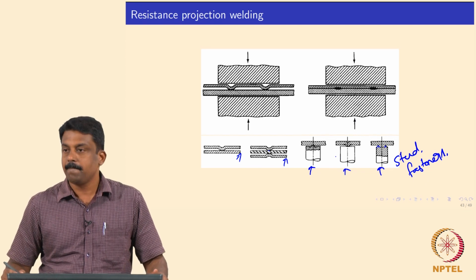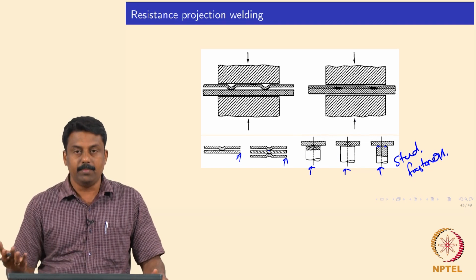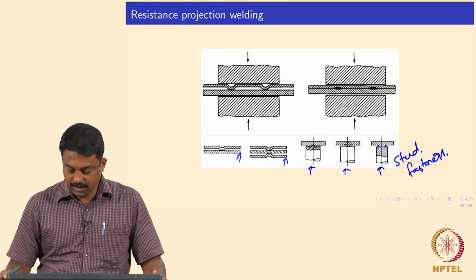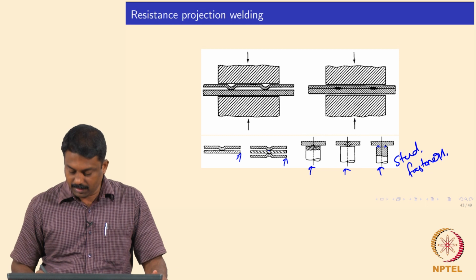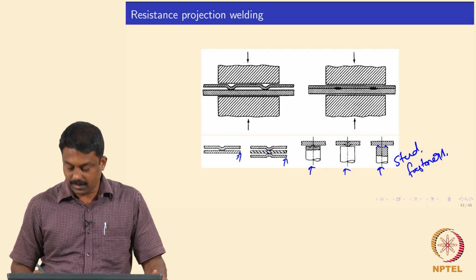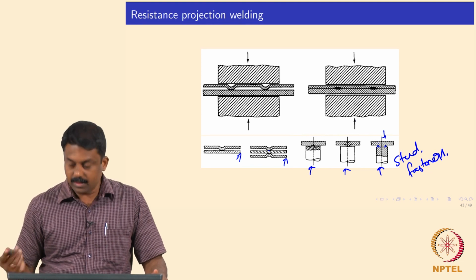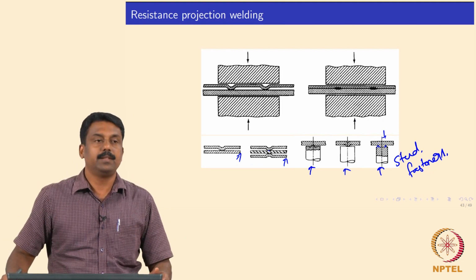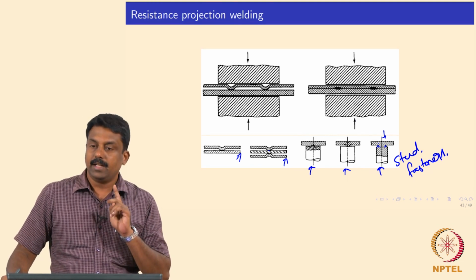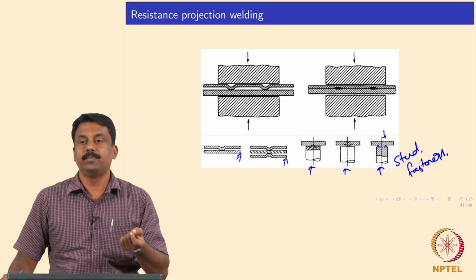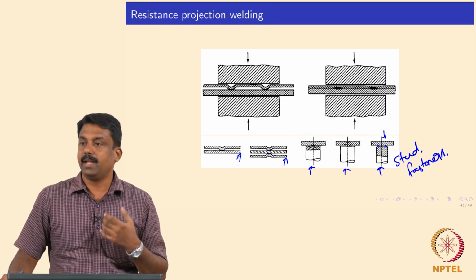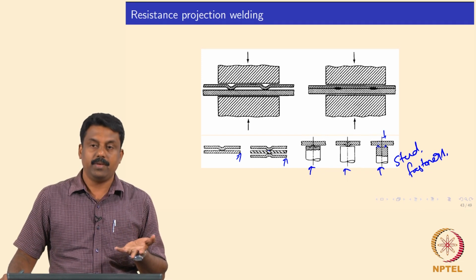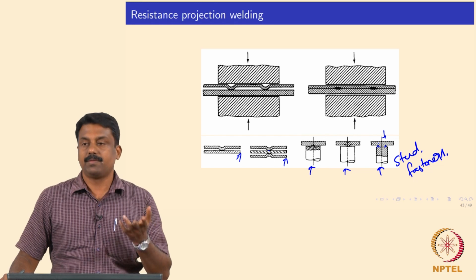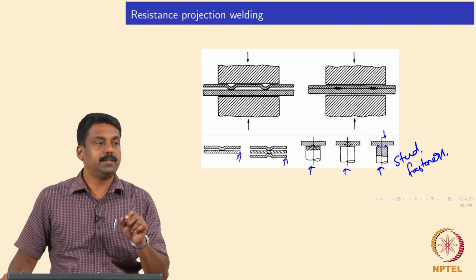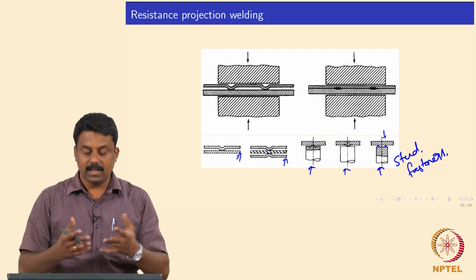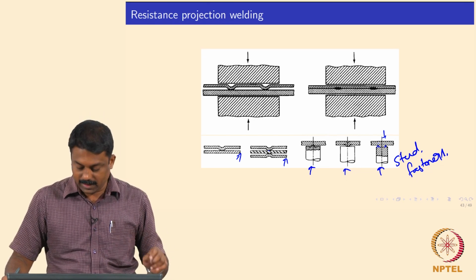These are various fasteners, and they will have to be attached to a solid bed, for example. You pass the current, and then you have a contact area leading to contact resistance, and subsequently you push and make a joint. Resistance projection welding with a slight modification in the discharge mechanism can be what you call capacitor discharge welding, which is very commonly used to weld studs, fasteners and thermocouples to any substrate. That we will see in the last slide.